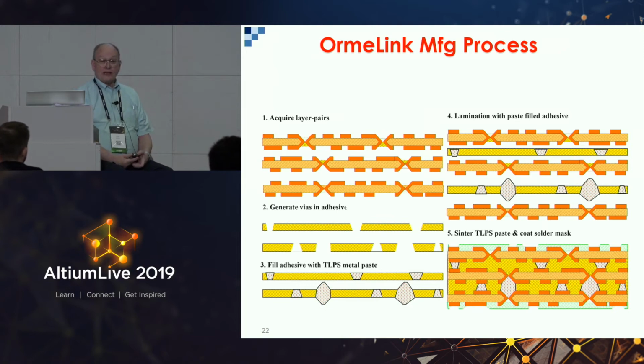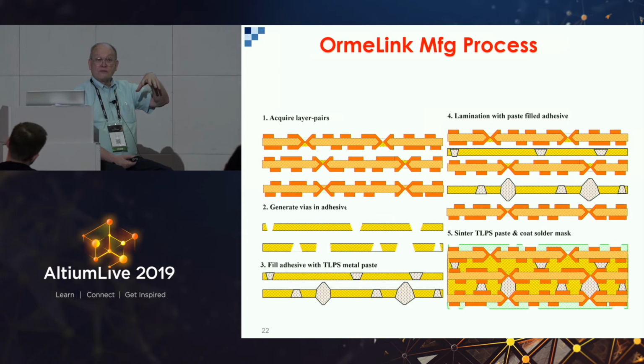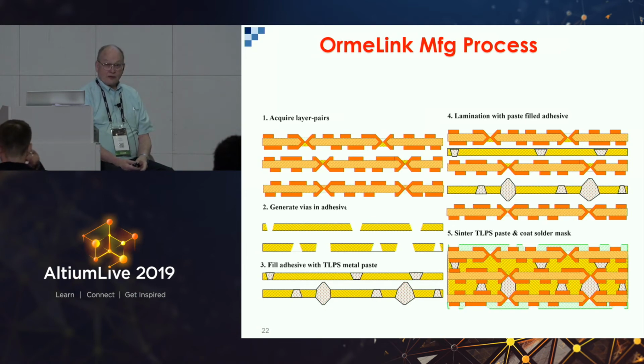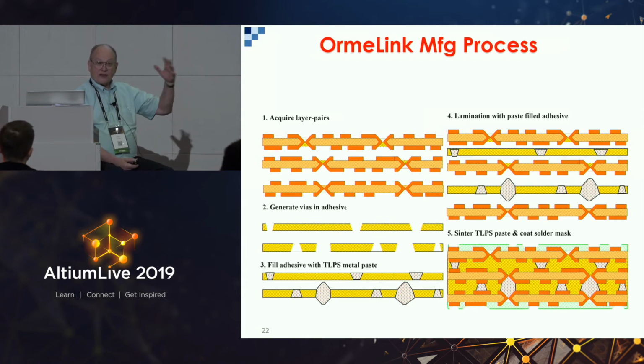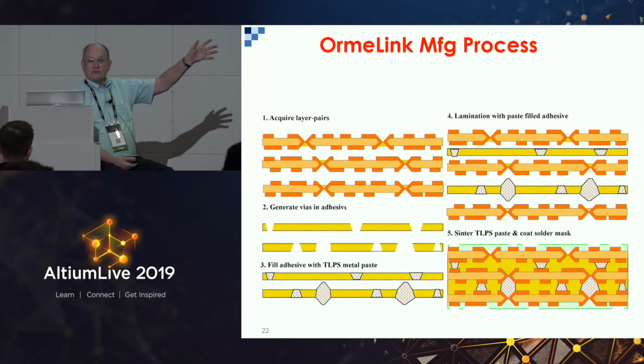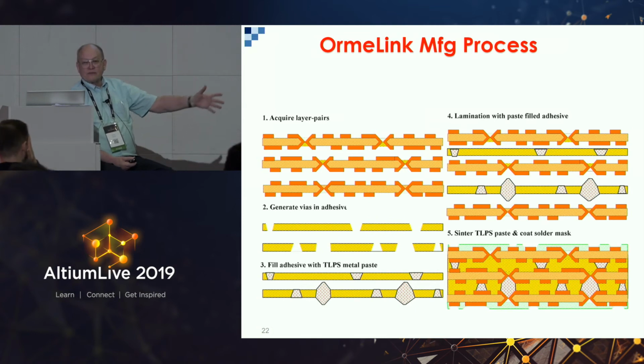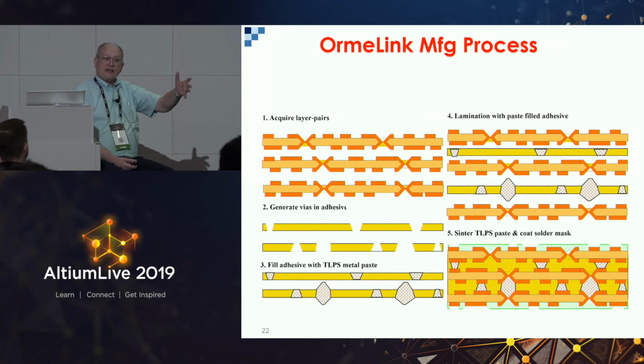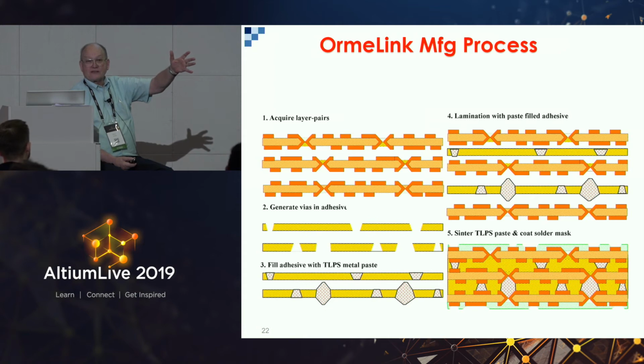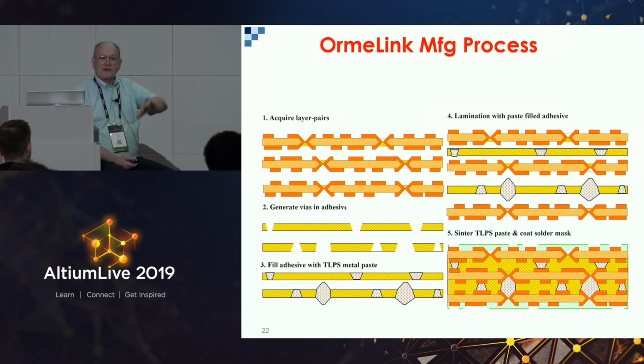It's pretty interesting because we had a plant there that would do roll-to-roll polyimide, and they used excimer laser to drill 25 micron holes about 20,000 per second. And it cost the US public and the military about $100 million US for this state-of-the-art factory to make all of these circuits. And it was interesting because of the vacuum sputtering, to make something stick to polyimide, they would laser drill the holes. Then they would put them in this 2-story vacuum chamber and sputter titanium on them. And then the next vacuum chamber would sputter copper on them. We put down about 1,000 angstroms of titanium and about 3,000 angstroms of copper, and then we would go through electroplating up to 5 micron.